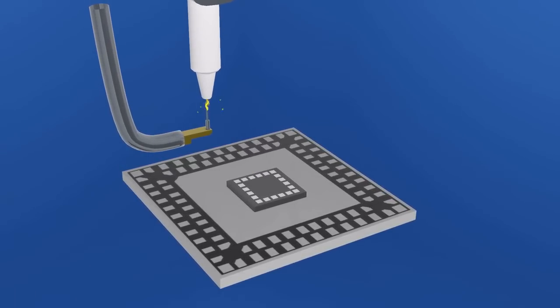In the bonding process, the end of the wire is first heated to the melting point. As the end of the wire melts, it forms a ball on the end. Since copper easily oxidizes, the copper bonding process requires an inert gas.